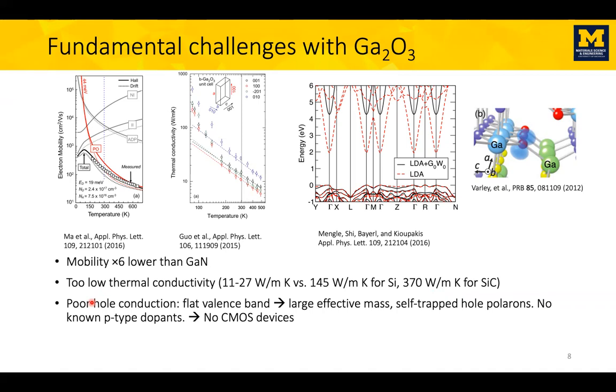Another major limitation, though, is that even though the material can be doped N-type, there are no reports of P-type doping. And we understand the reasons. The reason is that if you look at the bands of these materials, the curvature of these bands tells you how easy it is for electrons and holes to move in this material.